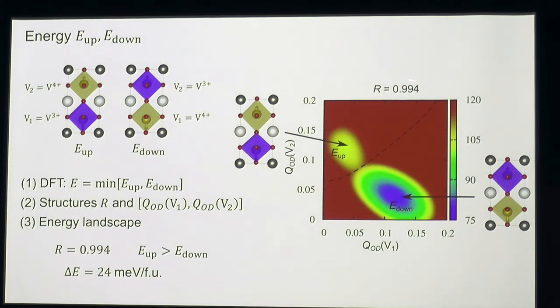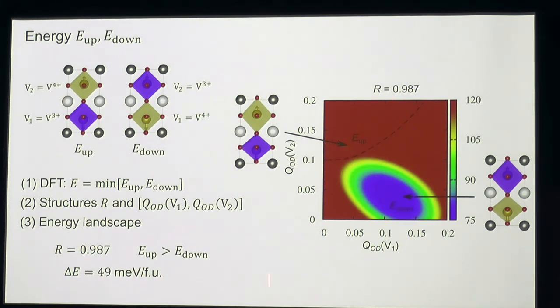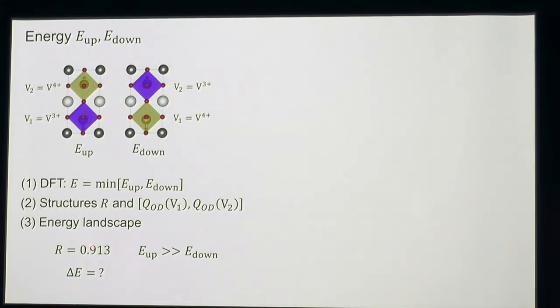Then we decrease R a little bit by shrinking the volume of the polyhedron at the bottom. We can see that the R polarized state is less stable, and there is an energy difference between the two polarized states. If we decrease R further, the energy difference increases further. Here, we should mention that for this R value, this local minimum is very shallow. But we should also note that this R value is still far away from the optimized R value, which is 0.317. For such an R value, we cannot generate such an energy landscape because the R polarized state is no longer a local minimum.